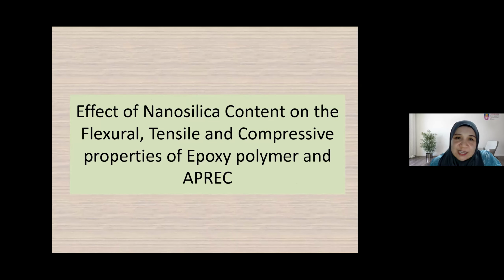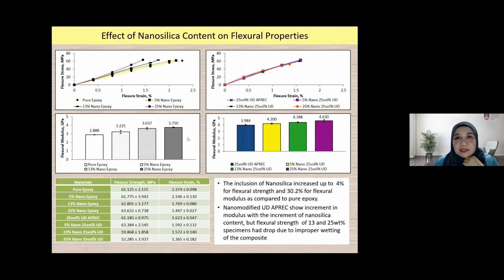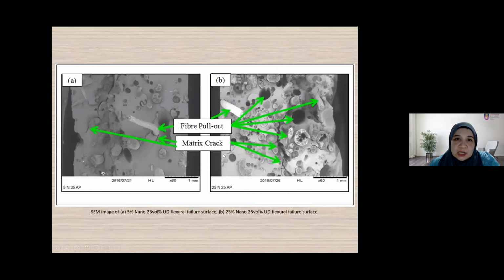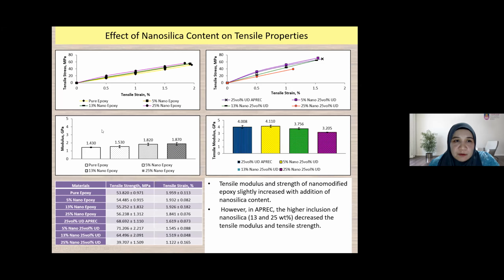We can see almost similar results for adding the nanoparticle. We can see the increase in flexural modulus of the polymer itself, and the flexural modulus increases for the Arenga pinnata composite. For the tension, the Young modulus increases from 1.4 to 1.87 for epoxy if we add up to 25% nanosilica.